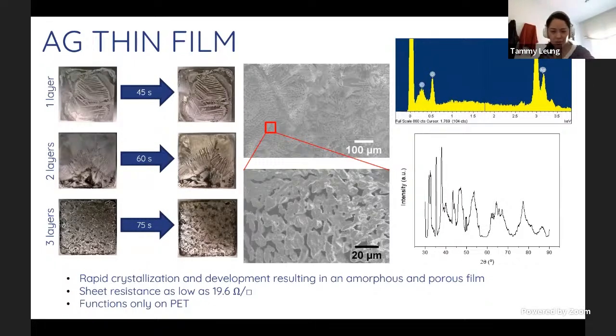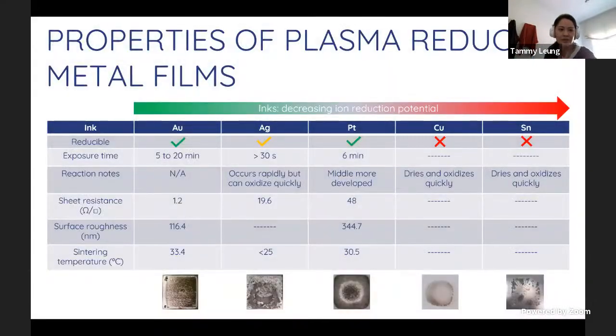However, XRD showed a completely different story, where the diffraction pattern didn't match many of the references. Therefore, there were impurities in the formation of this film. Because of these results, the ink was no longer used for further experimentation, and it is well known that silver nanoparticle inks are already available and optimized for inkjet printing.